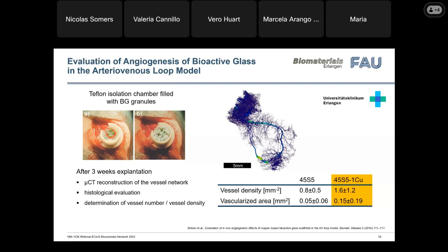In this case, an arteriovenous or AV loop model was used, which is an in vivo tissue engineering approach for generating vascularized tissue. The AV loop is placed into an implantation chamber, which here is made out of Teflon. Then this chamber is filled with bioactive glass granules mixed with fibrin, for example. And in this specific case, copper-doped 45S5 was also used. This was implanted for 3 weeks.